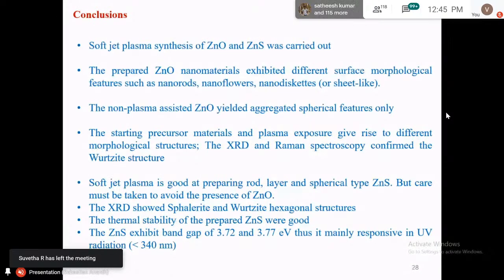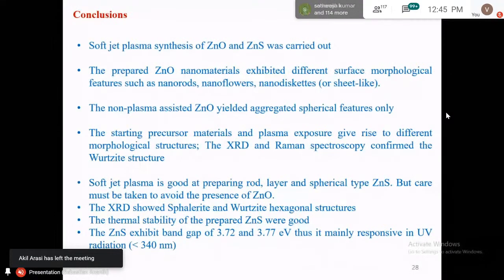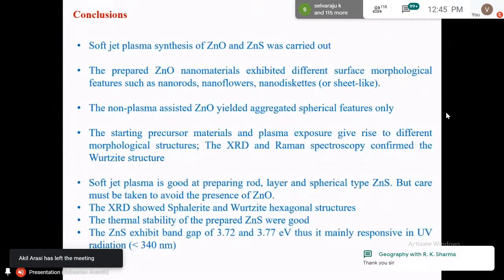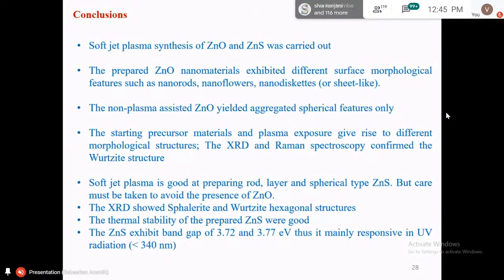But as compared to zinc sulfide, zinc oxide was better for engineering the surface structure. Zinc sulfide yielded only two or three kinds of surface morphology. And the zinc sulfide exhibits band gaps of 3.72 and 3.77 eV, so it is mainly UV responsive.